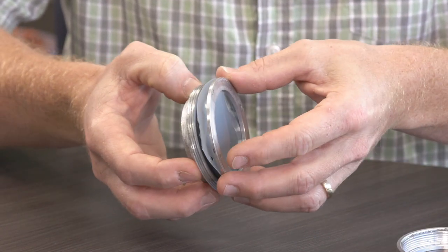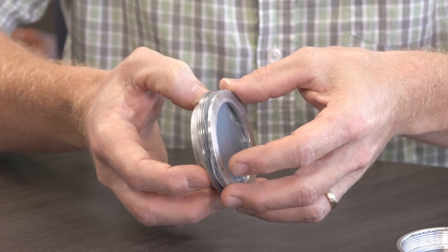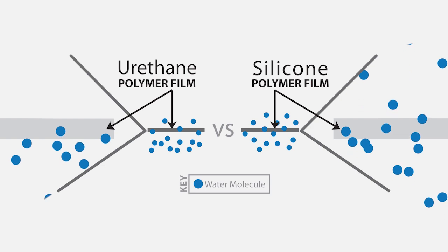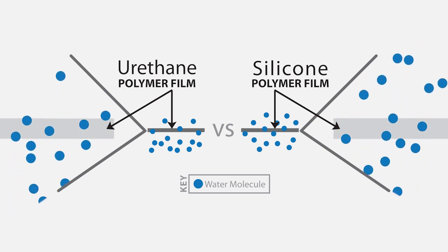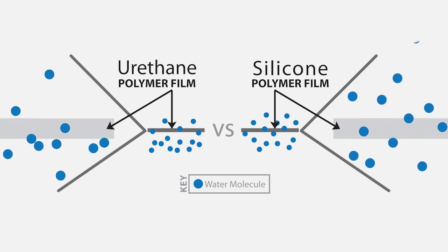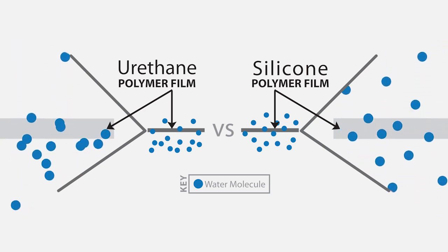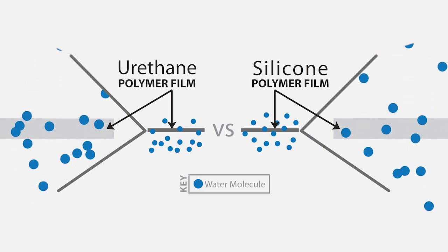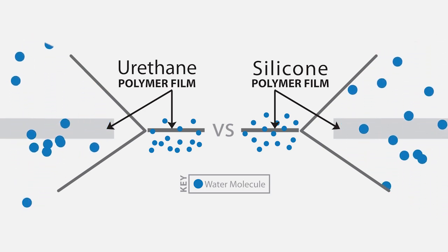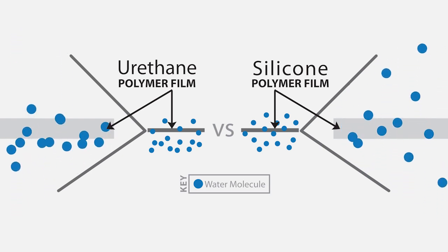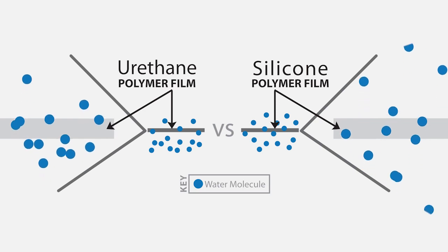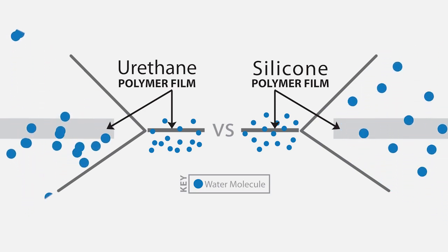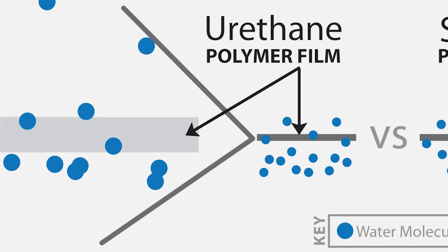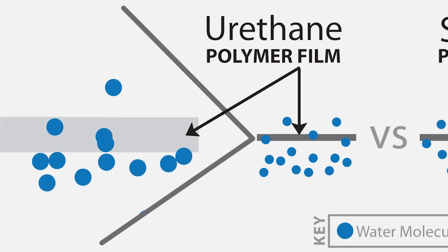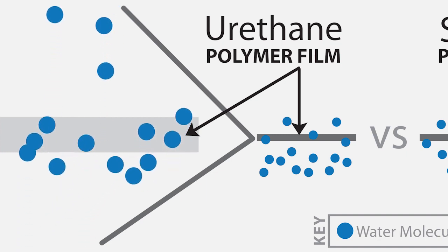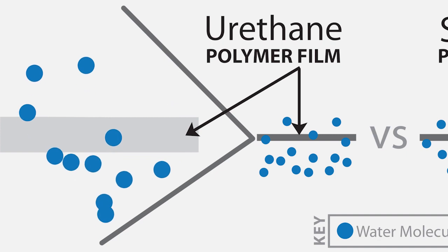This is the fixture used to conduct ASTM E1653. This illustration shows how the tests function to measure the water vapor permeability of a polymer. There are some variations of the test, but for simplicity, we will illustrate method and condition A, where water is placed in the cup and the cup is placed in a desiccator with near zero relative humidity. As water vaporizes in the cup, it interacts with the polymer. Depending on the polymer, different levels of these water molecules will attach to the surface and dissolve in the polymer. The water molecules will be drawn to the outside since the desiccant has lower relative humidity.